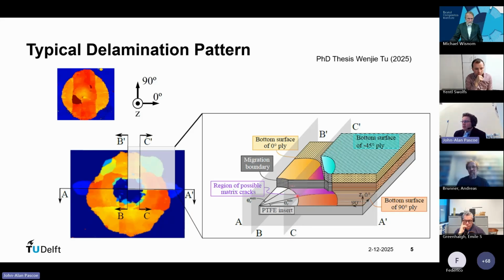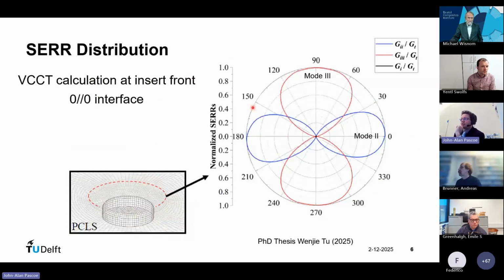And then you see this kind of purple shaded area in between. That's an area where, if you look on the fracture surface, you see a lot of matrix cracks. So it seems to be trying to deflect out of the interface it's in, but it can't quite break all the way through. It is being trapped. And then you see that eventually, if you get far enough out, it manages to find its way up to the 45-degree ply, because this was a quasi-isotropic layup in the end. So it's basically migrating up 2 plies and then continuing in this region in the 45-degree ply, or below the 45-degree ply.